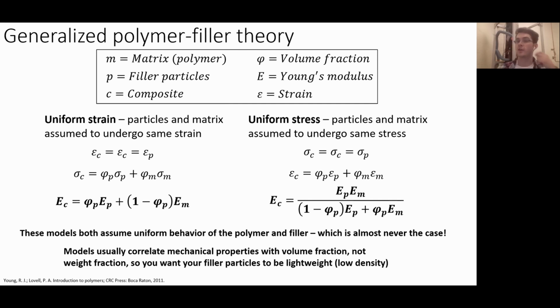On the other hand, we can assume that the particles in the matrix are undergoing the same stress, and that gives us more of a series rule of mixtures, something similar. It's also a weighted average of the polymer and the particle filler modulus as well. So these models both assume uniform behavior of the polymer and the filler, which never happens in reality. They also assume perfect adhesion of the particles to the polymer matrix, which again, as you can imagine, is very difficult to achieve in reality. Something interesting to note is that we always look at volume fraction rather than weight fraction for polymer filler systems. So you want your filler particles to be lightweight, as generally a lightweight composite is more desirable than making something heavier.